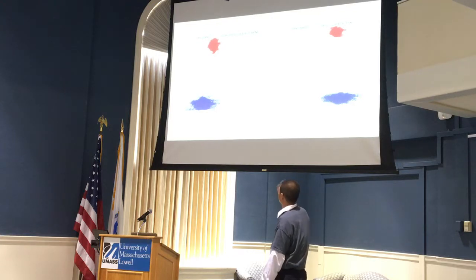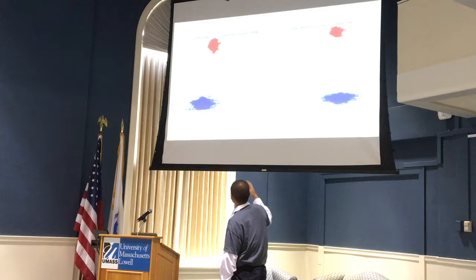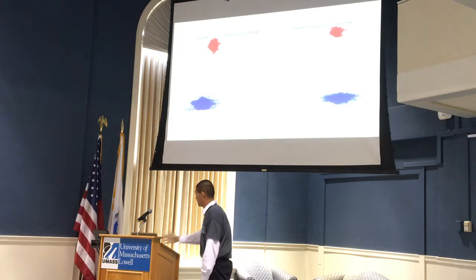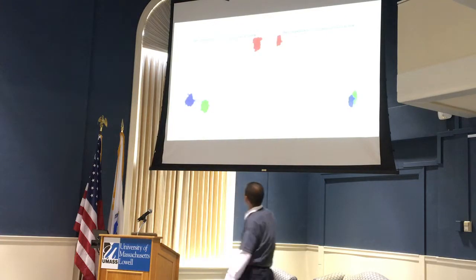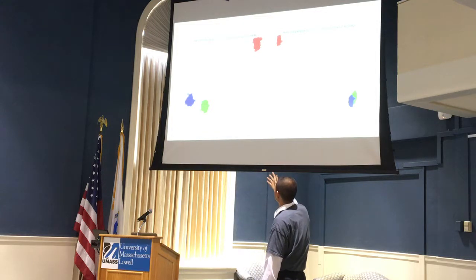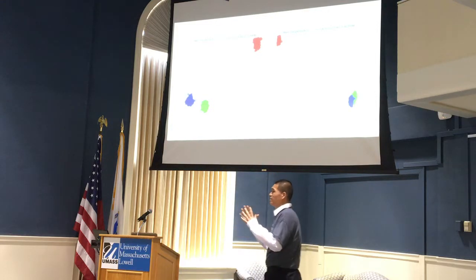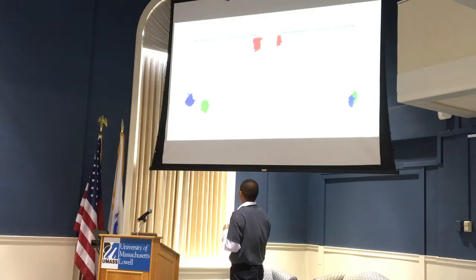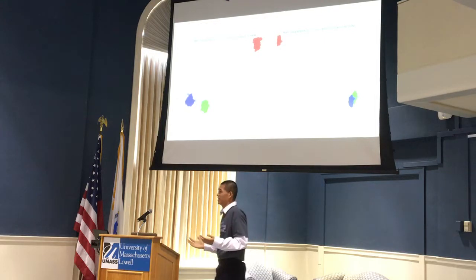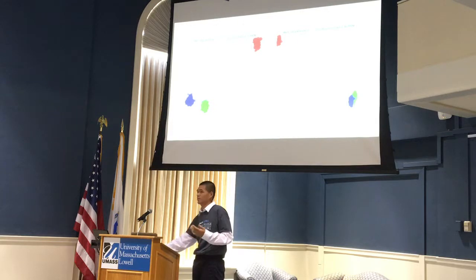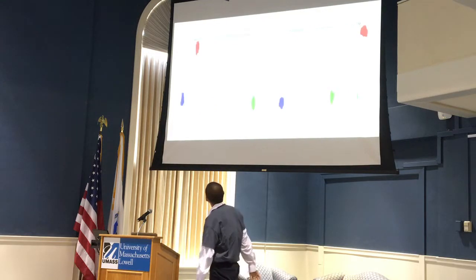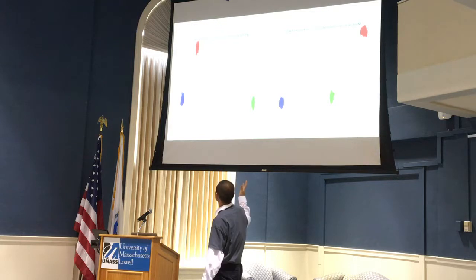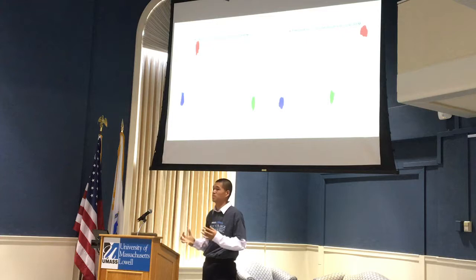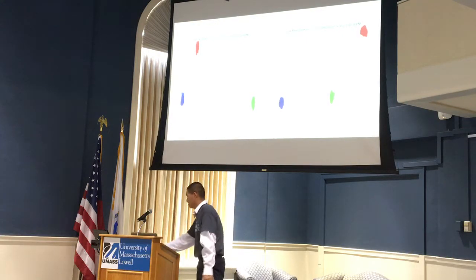This is in terms of our screw speed, or screw cross-sectional area versus screw speed. And basically, again, it doesn't look very good for the Fractal screw. However, when we go back to our melt temperature, we still see a very tight distribution, and again, it might not be a good indication of whether there was surging actually happening. So again, for our die temperature, we see the narrow distribution. We wanted to see some sharp transitions or something varying. Again, it seems to be very nice.